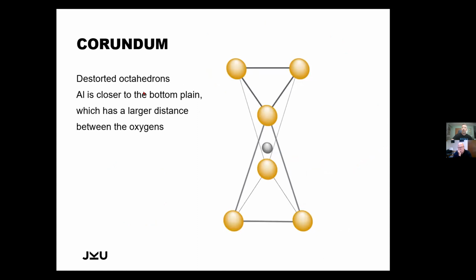If we look a little bit closer into the distortion that we have in this lattice, then we have these 3 oxygen atoms which form a triangle, and on top we have the next layer which also forms a triangle, but in this case the distance between these oxygens is a little bit smaller than in the lower layer, and the aluminum, which is here in the middle, is a little bit shifted towards the lower layer. So it's not perfectly symmetrical, but we have a distortion. And this is very important to understand the color and the different optical properties of corundum when we look at it at different angles.